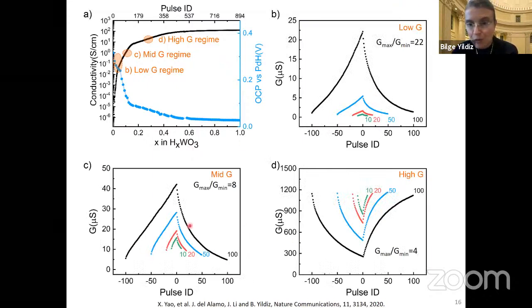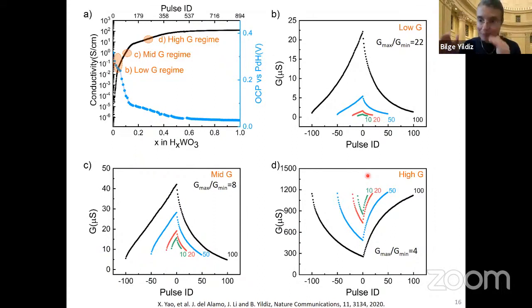And you can see these three batches of curves that tell us that both the maximum to minimum conductance modulation that you can obtain with the same amount of pulses, and the shape of the curve, that is the symmetry of the curve, depend on which regime you are functioning the device in. So without going into too much detail, the point being we want high absolute resistance and symmetric potentiation, depotentiation, that favors us to run the devices in this low protonation regime. Okay, so that's this panel. More symmetric curves and relatively higher maximum to minimum conductances that we can obtain.